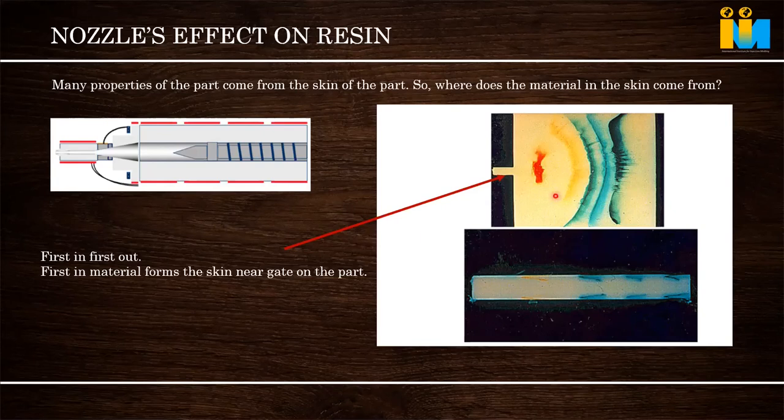And a study was done to understand this. A molding machine was running in white color. We dropped a small master batch, first red color, and after 1 or 2 seconds we dropped yellow color, then blue color, green, blue, like that, to understand where it is going. So the first granule that was put, the small master batch, stays in the gate. Next, what is going away? It shows that the first entry material stays near the gate and makes the surface of that entry area of the part.